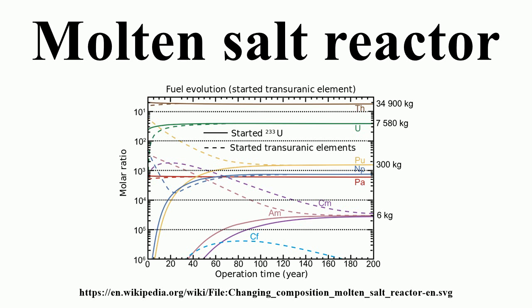The fuel for the MSRE was LiF-BeF2-ZrF4-UF4. The graphite core moderated it, and its secondary coolant was FLiBe. It reached temperatures as high as 650 degrees Celsius and operated for the equivalent of about 1.5 years of full power operation.